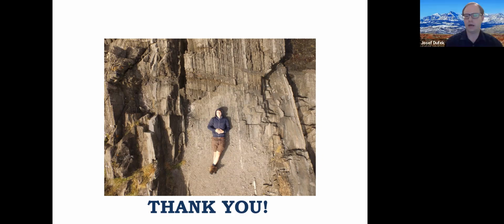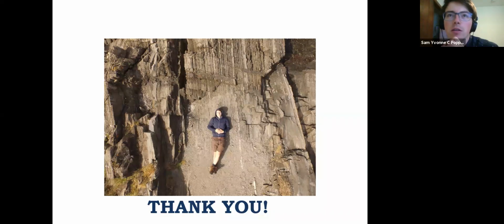No. Larry Mastin writes that 32 years ago for his PhD, he studied the surface displacements above a shallow dike in a box containing a mixture of flour and sugar. The region above the dike top began to subside to form a graben once the first cracks formed at the surface. But before those first cracks formed, there was no obvious subsidence. Did you notice a similar sequence in your experiments? So, yeah, with that difference that we don't get this pervasive subsidence at the surface above the dike tip, and Olivier Galland has talked a lot about that as well, that doesn't happen in their experiments.